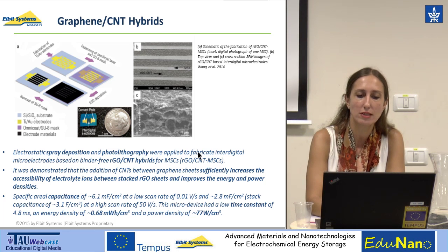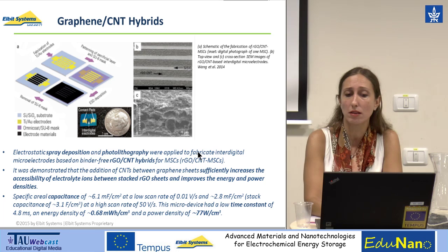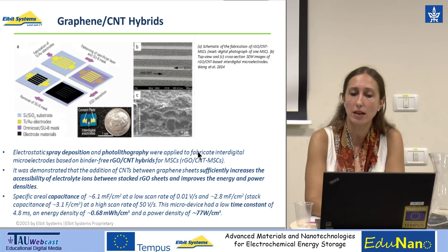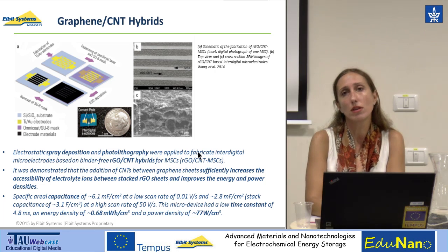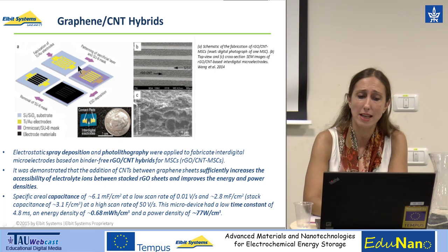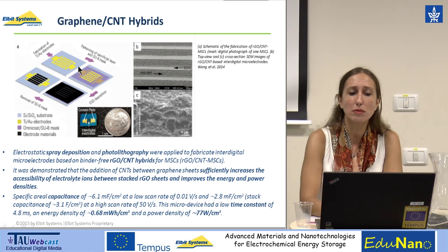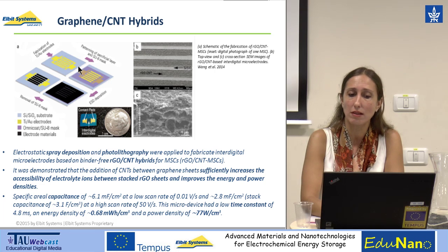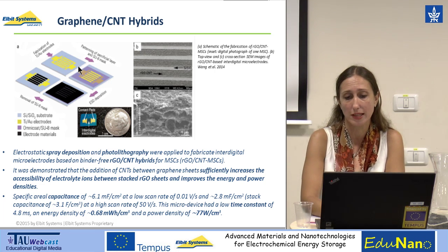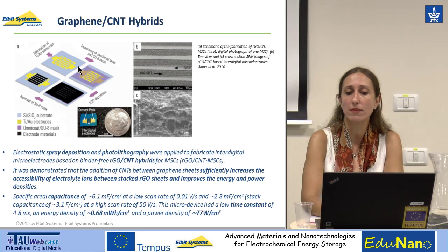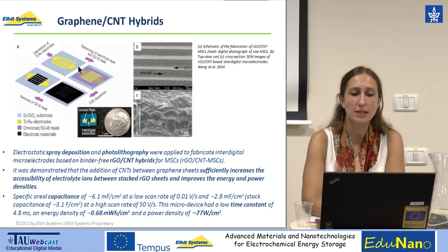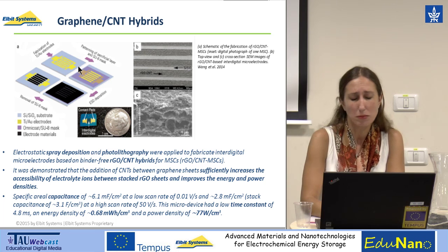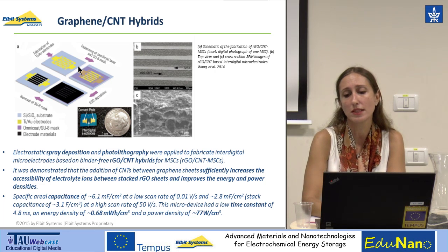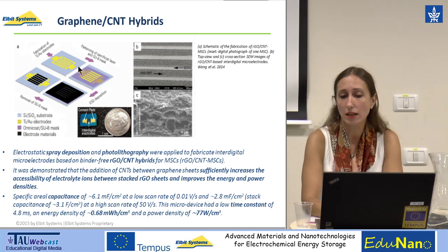So we are talking about 6.1 millifarad per square centimeter at a low scan rate and 2.8 millifarad per square centimeter, having an overall stack capacitance, but look at the size of the stack, of 3.1 farad per cubic centimeter at a high scan rate of 50 volts per second. So this micro device had a low time constant of 4.8 milliseconds and energy density of 0.68 milliwatt hour per cubic centimeter and a power density of 77 watt per cubic centimeter.